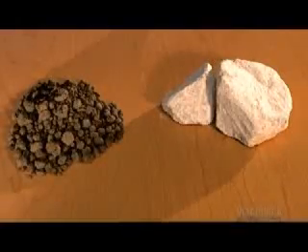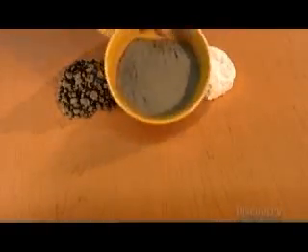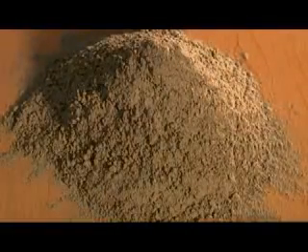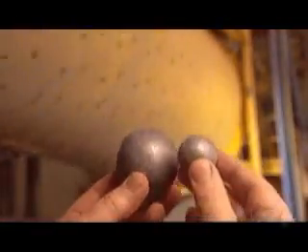The last stage of cement making is called finish grinding. They add some gypsum to the clinker — the precise amount varies with the type of cement they're making. Gypsum delays the cement setting time so that it can be worked for up to 2 hours before hardening. The cement mills are called ball mills because they contain metal balls, about 150 tons of them in the largest mill. As the mill rotates, the balls crush and grind the clinker and gypsum into a fine powder.